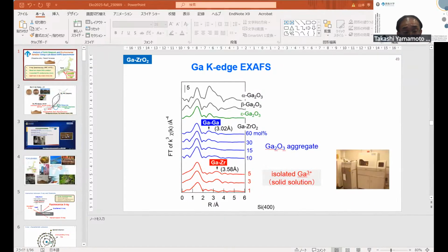Next, we recorded the gallium K-edge EXAFS spectrum. This is the radial structure function. We can check the different types: at low dopant amount, the second peak appeared around here, and at higher loading amount, the change differs. By curve fitting analysis, at low doping amount, the second scatterer is zirconium. It suggests the gallium ion is incorporated into the bulk. But at high doped amount, this shape is close to that of gallium oxide. Maybe it is aggregated.